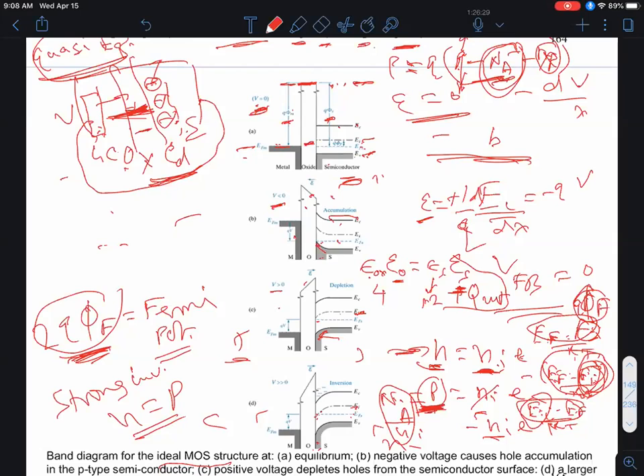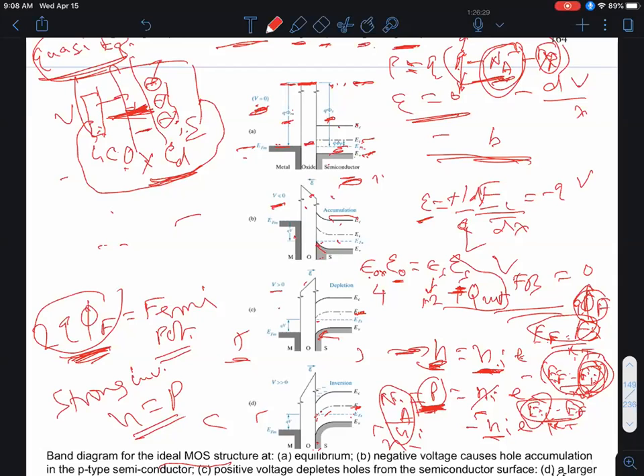But if you keep going, at some point the band bending will be enough that E_i will bend as far below the Fermi level as it was above the Fermi level. Now that's relevant, that's known as your Fermi potential, q phi_f. That's relevant because if you look at the expressions for electrons and holes we saw in chapter 4, it's given by n_i times e to the power (E_F minus E_i) over kT for electrons, or you flip the sign for holes. And E_F minus E_i is, of course, this quantity phi_f, which I'm calling the Fermi potential. In other words, the Fermi potential is a measure of how strongly the material is doped, either P-type or N-type. In this case, of course, it's doped P-type.